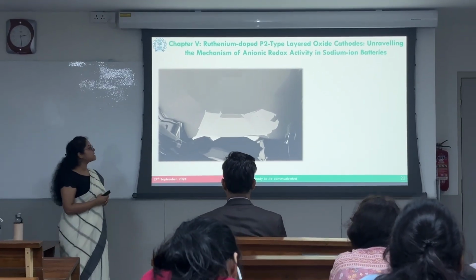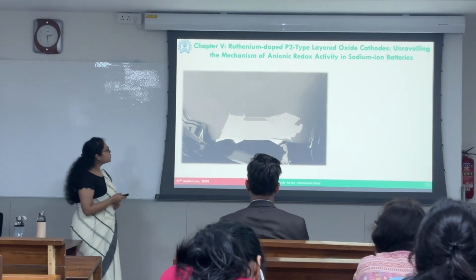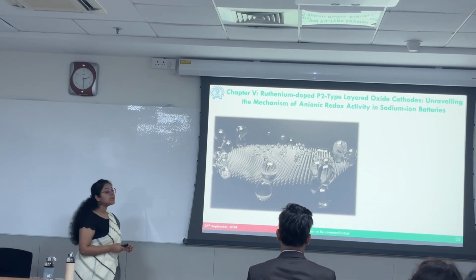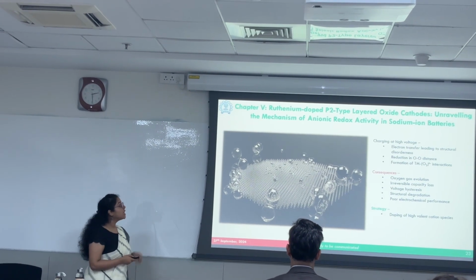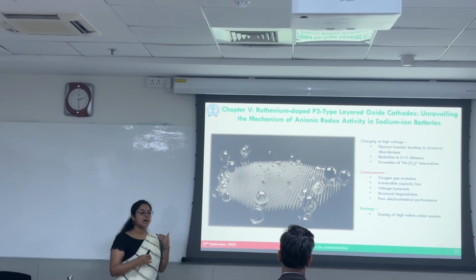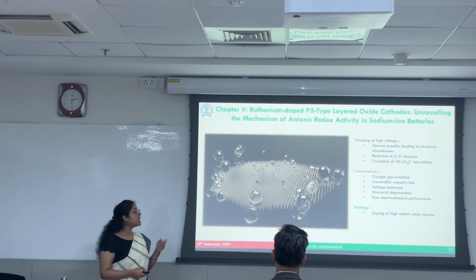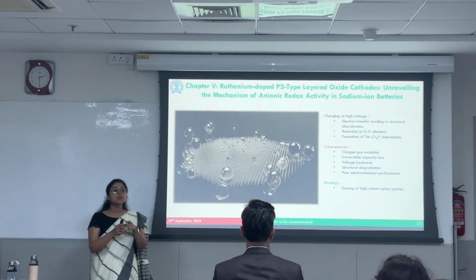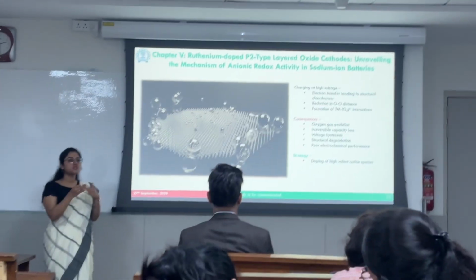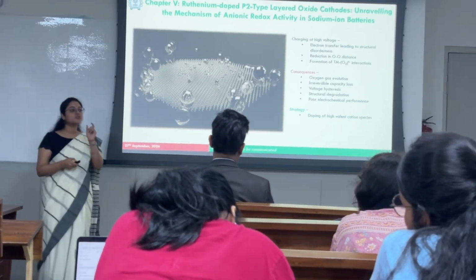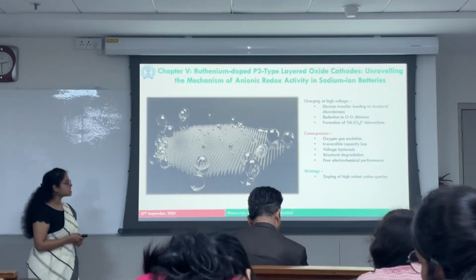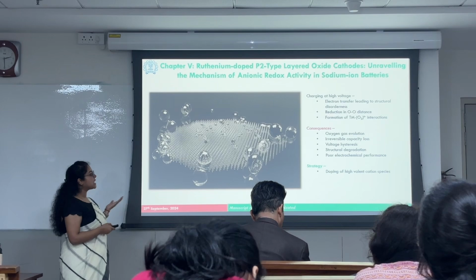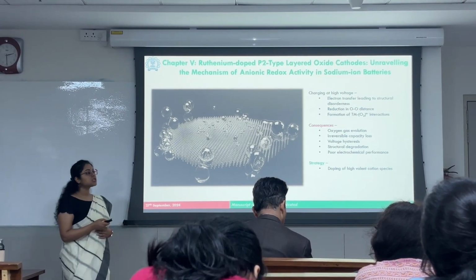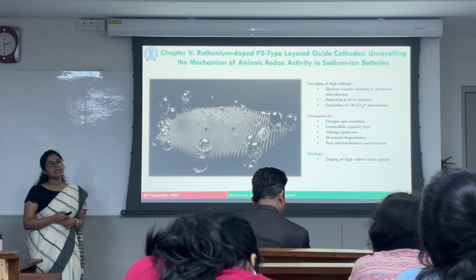So, in the next working chapter, we try to unravel the mechanism of anionic redox activity. We have seen how gas evolution during electrochemical cycling is a serious problem in terms of safety. This happens when we are charging at a higher voltage. Apart from the phase transition, there is also electron transfer that leads to structural disorderness, a reduction in the oxygen-oxygen bond, and also the formation of transition metal and peroxo-like species, leading to consequences such as oxygen gas loss, irreversible capacity loss, voltage hysteresis, and structural degradation, along with poor electrochemical performance.